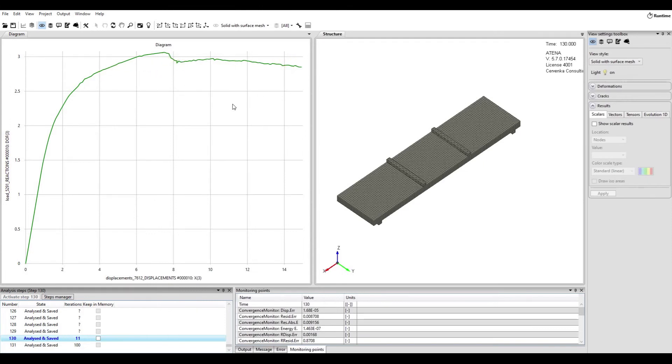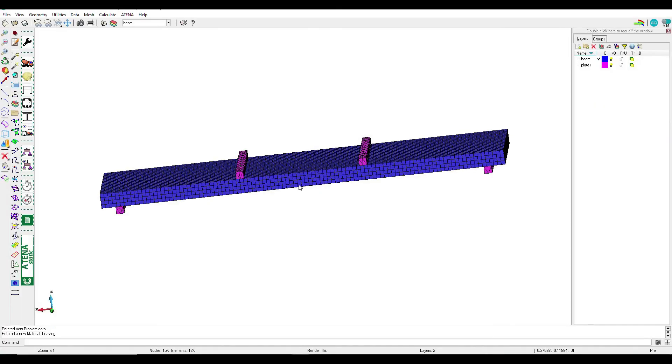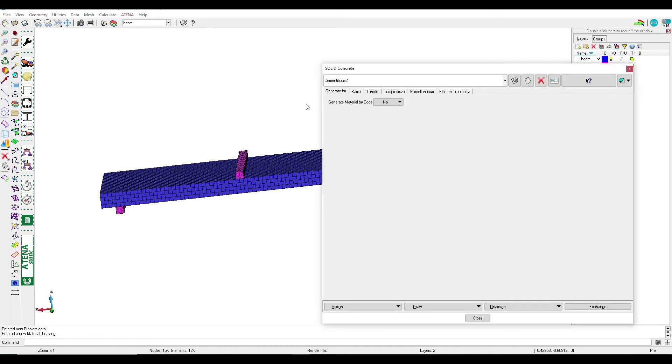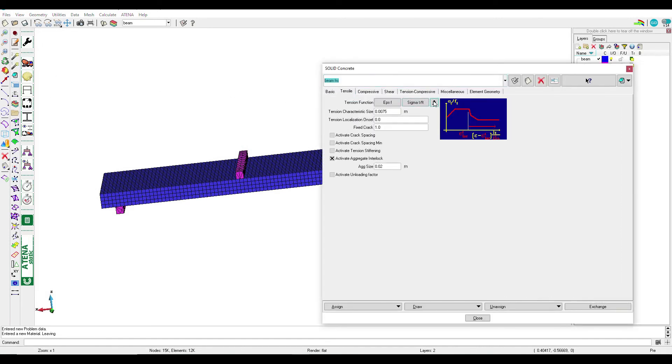We are so far from the softening part. With simple analysis we can directly understand that the initial value is very large, so we should directly shift 0.1 to a smaller value without any calculation.